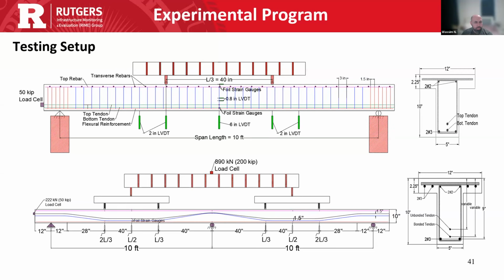And we had several beams tested with different combinations of tendons. We used both steel and CFRP. We used them as bonded and as unbonded tendons, and we made a full comparison between the two tendons to see how they affect the flexural behavior or other behaviors.